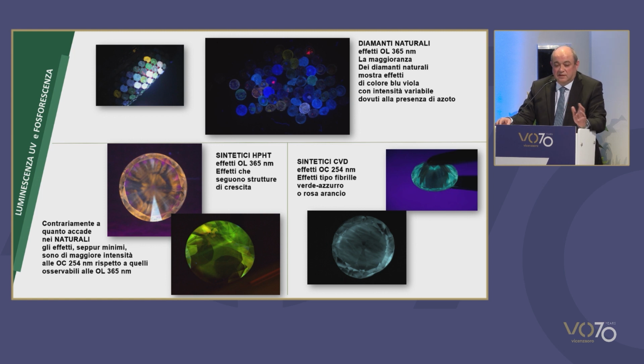Yellow, green, orange. I mean, this does not mean that it is a synthetic gemstone. It could be natural, but usually synthetic diamonds produce these colors. And they can be totally neutral with regard to the long wave. Things change when we submit them to short waves, 254 nanometers. You have to be in a dark room, and when you observe the gemstone, you will see a difference if you look at the diamond with the long or with the short waves.